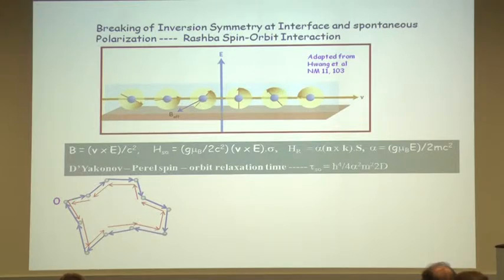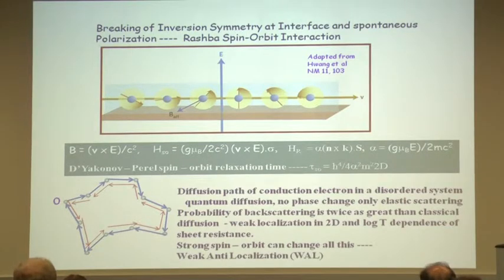This is called quantum diffusion in 2D, and this is what leads to the so-called weak localization. It's basically happening because of constructive interference between two partial waves. And what you see, an important consequence of weak localization, is a log of T dependence of sheet resistance at very low temperatures.